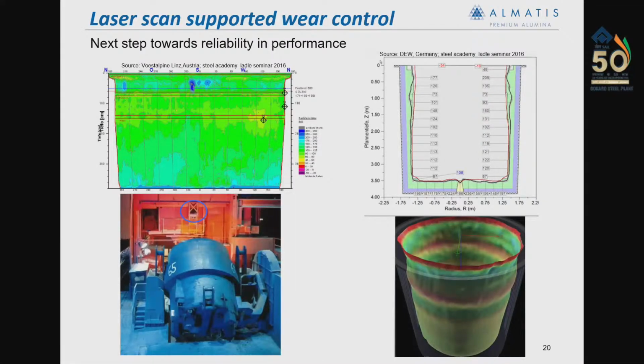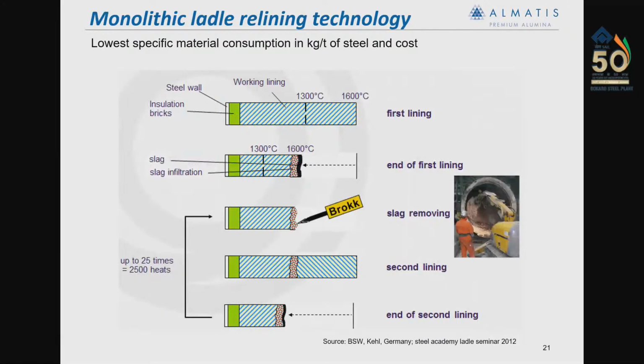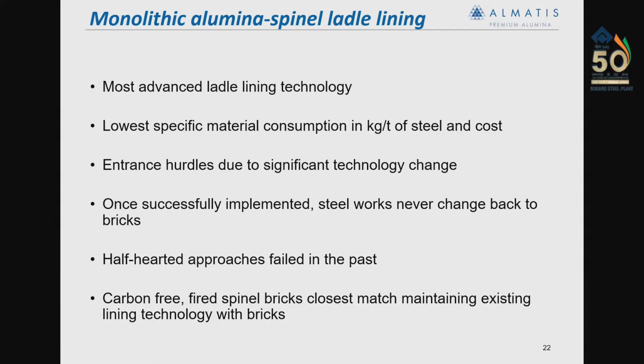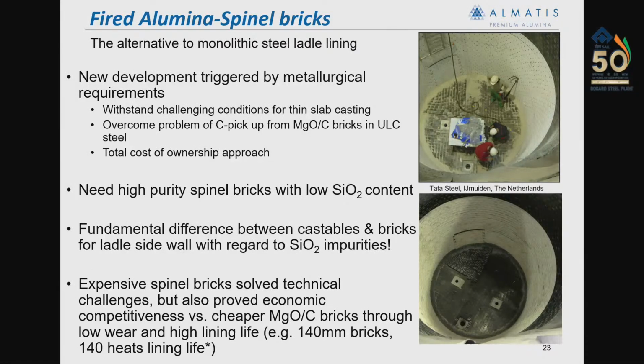But monolithic lining also gives you the relining facility and the recycled material reuse, all this facility also. You can build up on the leftover thickness and the wastage will be minimum. So the reuse part we can focus on. Monolithic is the really advanced lining, where if we see the global standard of where the lowest specific cost of refractory is catered, these are the monolithic linings. And in India, in the absence of these things, we are doing with fired spinel brick. And these are taken care of by the metallurgical demand and for thin slab casting also.